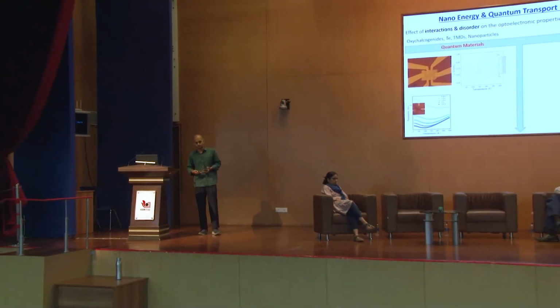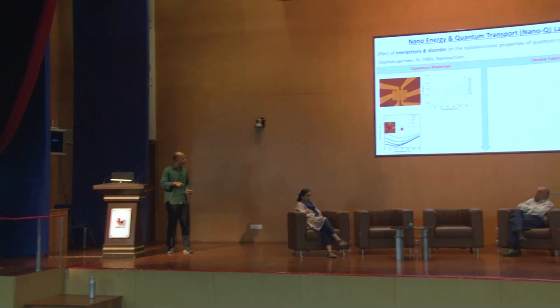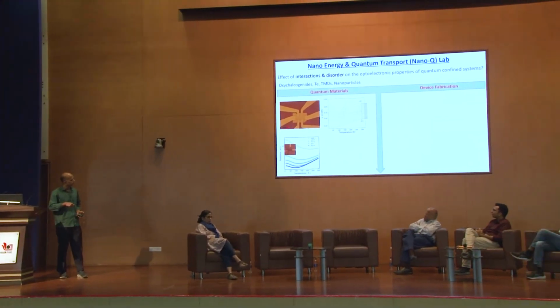And here what we found is that when you are changing the carrier density, again we are increasing the gate voltage, initially it was insulator type, but then as you increase the carrier density, you see a metal-like behavior. And this point, you can tune based on what your carrier density is in that system. But if you make this sample with just chrome gold contact, a different type of contact, which will give you a Schottky type of contact, then you may not see this phenomenon. You will always see insulating type behavior.